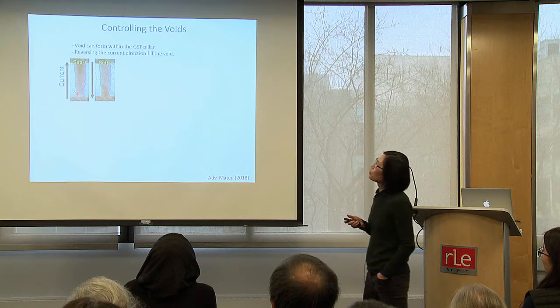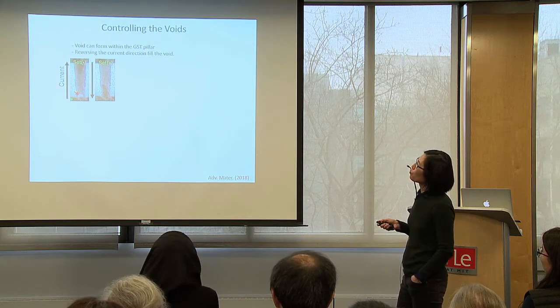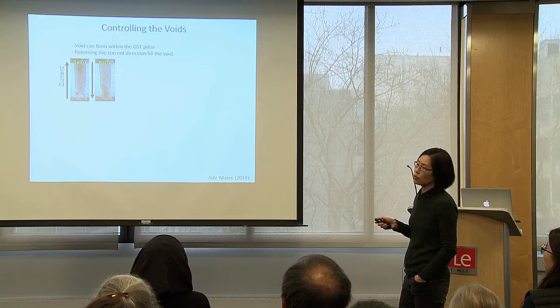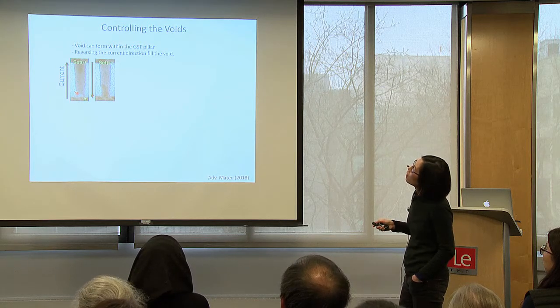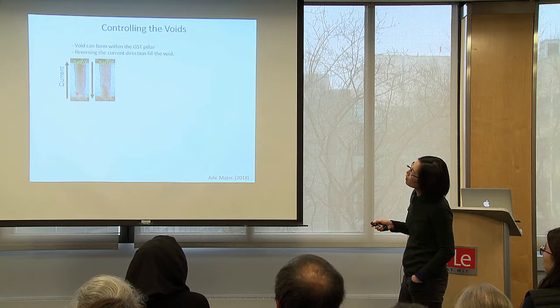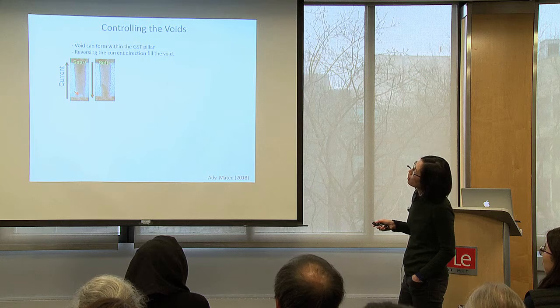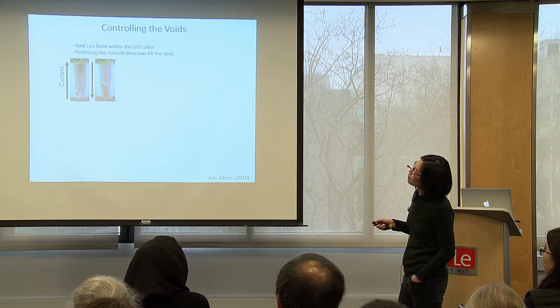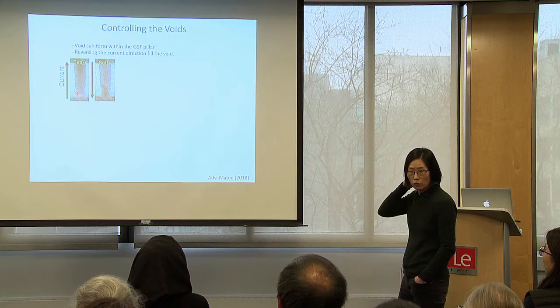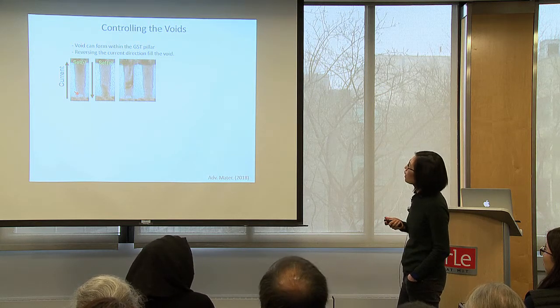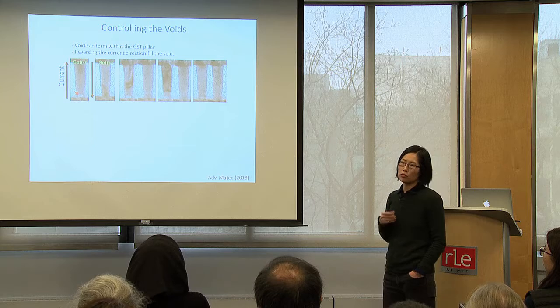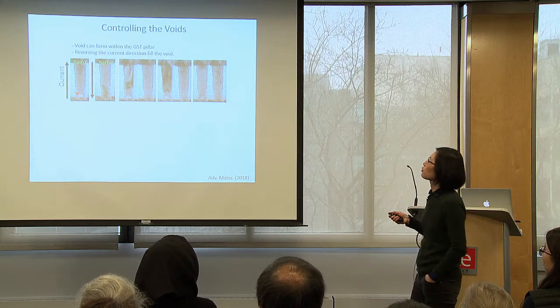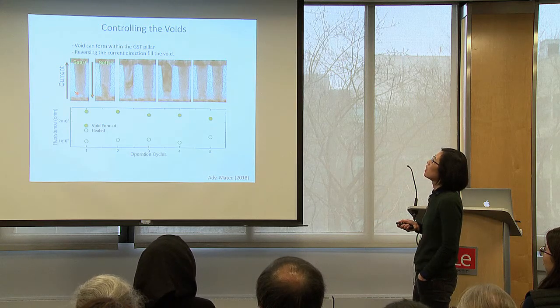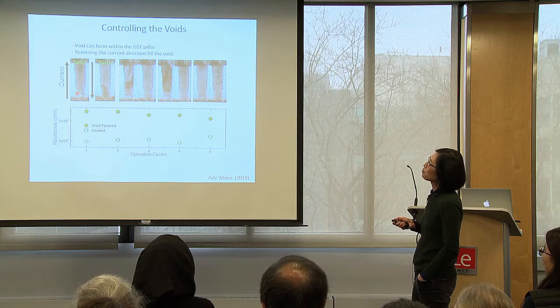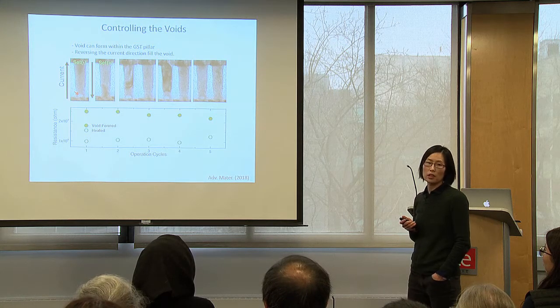The one thing we noticed was that you can form voids if you don't do this carefully. So here, the current direction is this way, and then we form a void here. Now, we can reverse the direction of the current, and then we can fill the void. And this is a pretty reliable, reproducible process. So now we're just reproducing it many times. And when you have a void, you have an empty space, so the resistance is going to be higher.